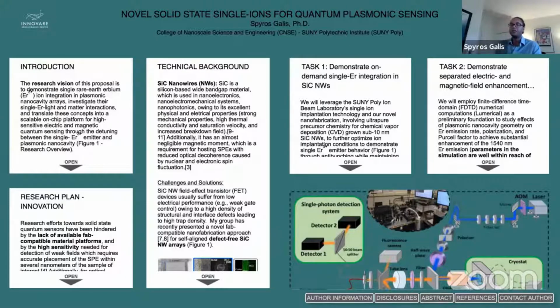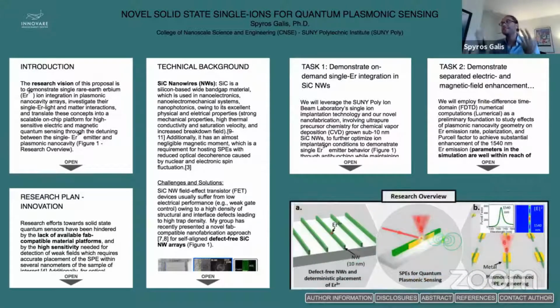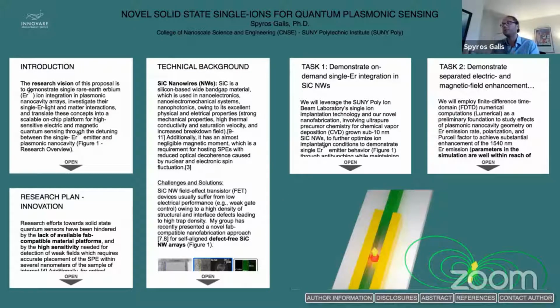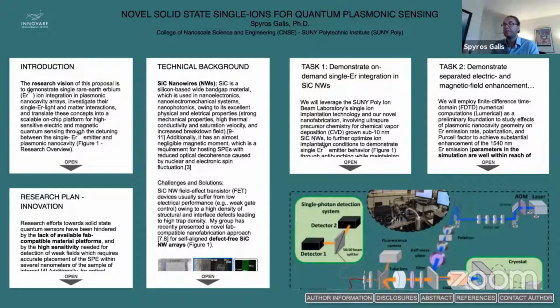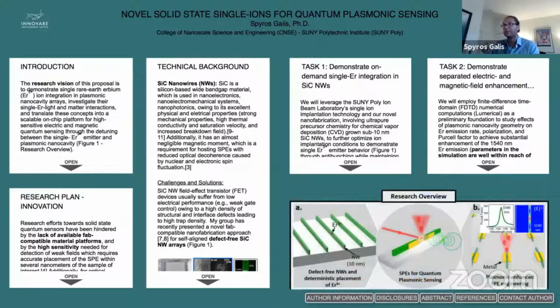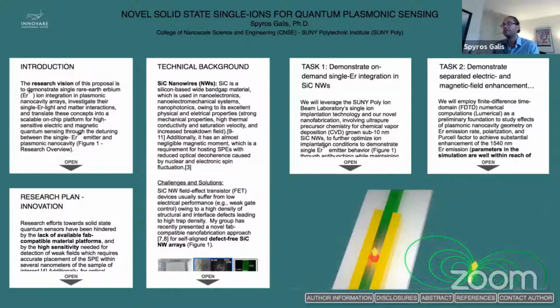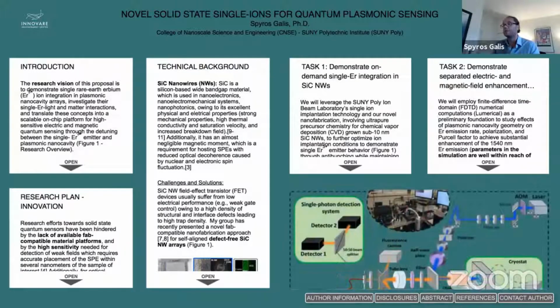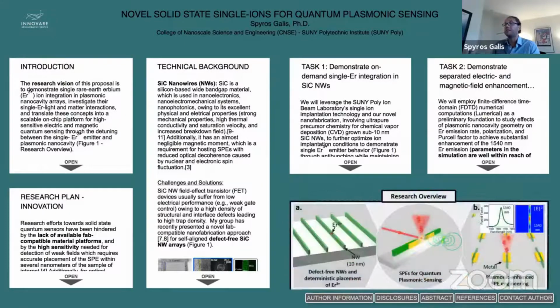And number two, just because we use certain sacrificial layers, let me put it that way, damage on the actual sample is minimized. This was demonstrated through the benchmark value that I mentioned about the absorption cross-section, which is enhanced by 2 orders of magnitude with respect to typical values in erbium-doped quantum materials. And by the time-resolved luminescence measurements, where we did not see any kind of change in the lifetimes between high and very low, cryogenic temperatures.